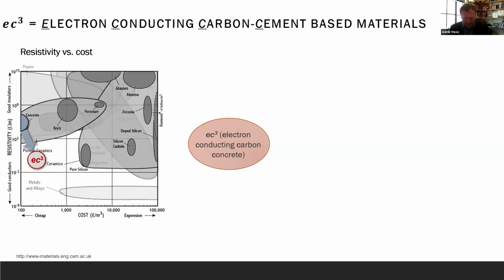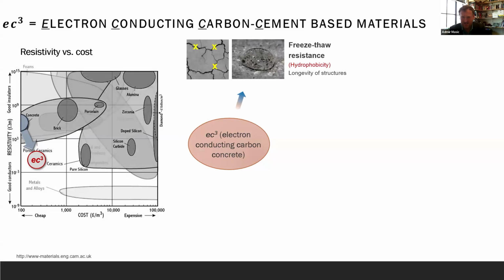Okay, now the applications of these materials are incredibly important. Here is another Ashby plot, between resistivity and the cost of the final product, where EC cube, you see, is on the order of pure silicon conductivity, so a conductive material, whereas the cost is not affected significantly because the amount of carbon black needed to make it conductive is very small. We are talking about a percolation threshold of about 2.5–3% to create these percolated nanowires.